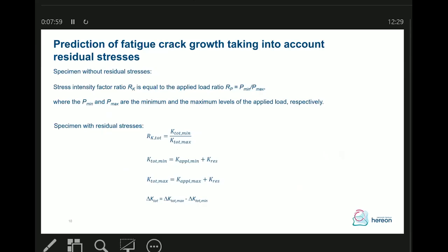We calculate the total stress intensity factor from the minimum load and maximum load, considering the residual stresses and stress ratio. In our case, to calculate the effect of residual stresses, R is not equal to minimum divided by maximum load. It's K min divided by K max, considering the effect of residual stresses. The residual stress intensity factor due to the presence of residual stresses we calculate using the weight function method. And if K min is less than 0, we just set it to 0 in order to represent the hard surface contact. But this is not the case in reality.